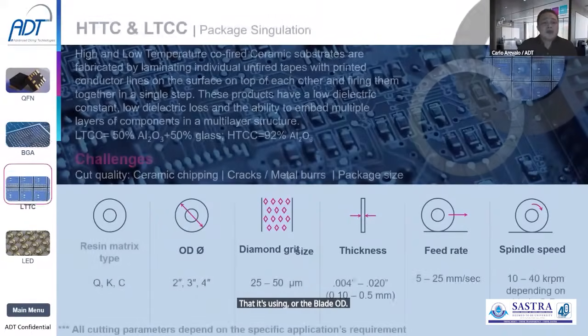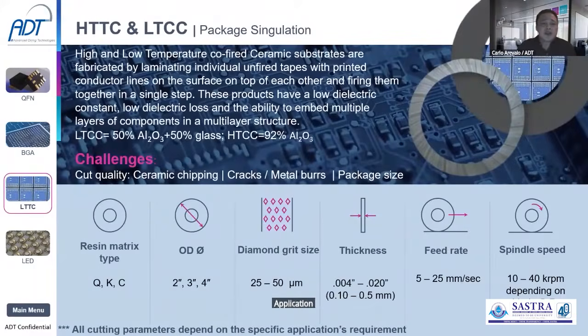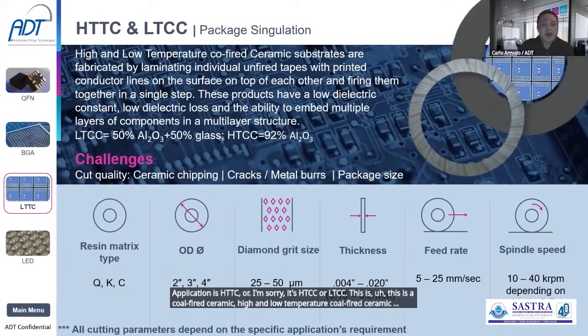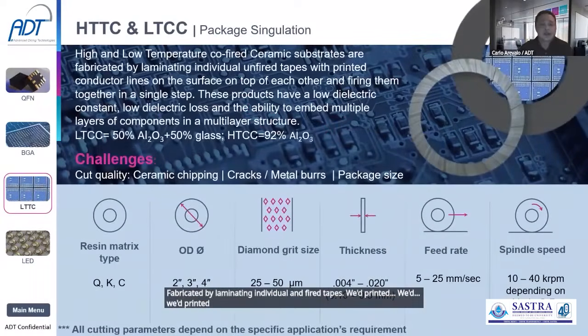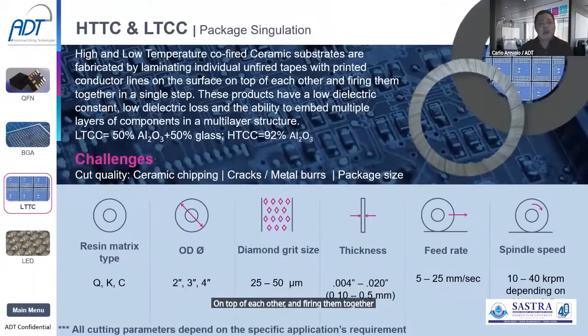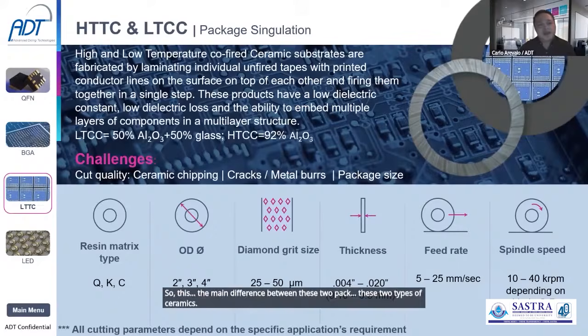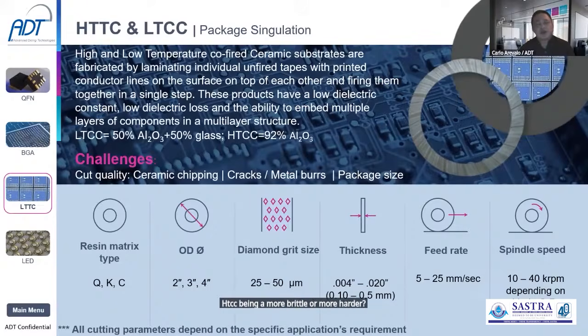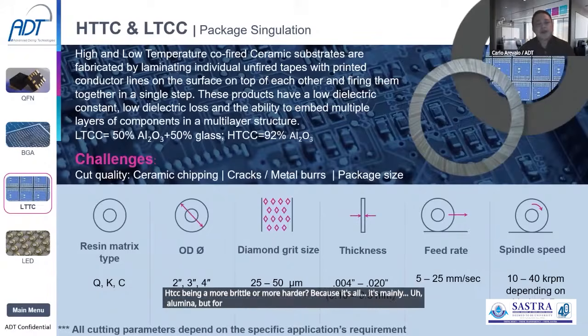Next to BGA application is HTCC or LTCC. These are high and low temperature co-fired ceramic substrates fabricated by laminating individual unfired tapes with printed conductor lines on the surface on top of each other and firing them together in a single step. The main difference between these two types of ceramics is that HTCC is more brittle and harder because it's mainly alumina, while LTCC is a mixture of alumina and glass.